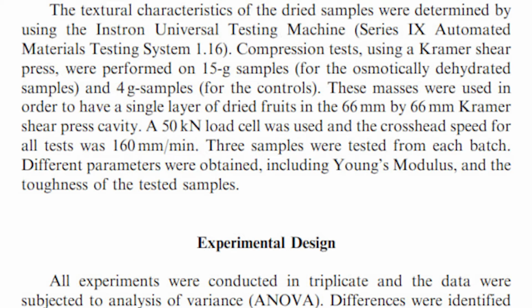The textural characteristics of the dried cranberries were determined by using an Instron Universal Testing Machine, Series 9 Automated Materials Testing System 1.16. Compression tests using a Kramer shear press were performed on 15-gram samples for the osmotically dehydrated samples and 4-gram samples for the controls. These masses were used in order to have a single layer of dried fruits in the 66 mm by 66 mm Kramer shear press cavity. A 50 kilonewton load cell was used, and the crosshead speed for all tests was 160 millimeters per minute. 3 samples were tested from each batch. Different parameters were obtained, including Young's modulus and toughness of the tested samples.